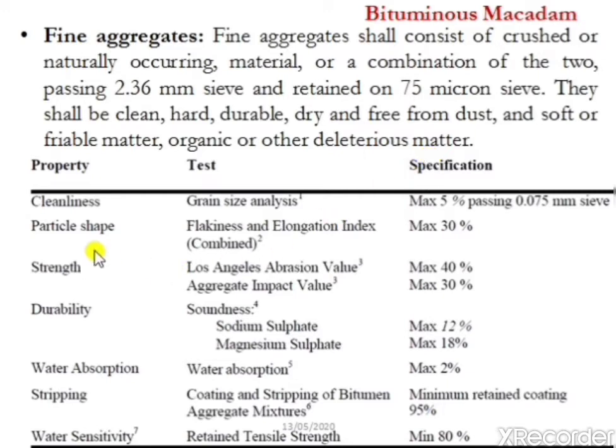The second property is particle shape. For particle shape, there is a test called the flakiness and elongation index. The maximum flakiness and elongation index of the material or aggregate should be within 30%, or the maximum is 30%. Next, strength.